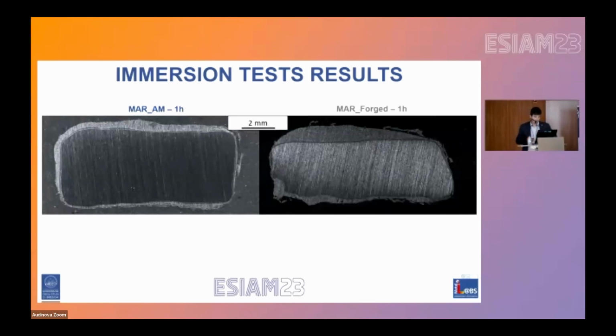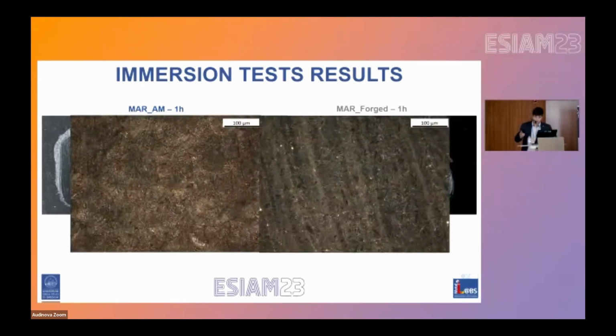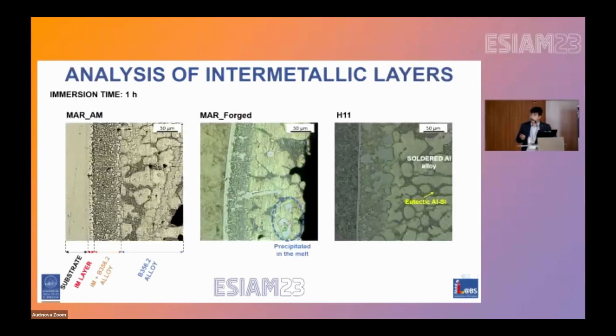This behavior could be correlated with the different speed of the reaction between the steel and the aluminum, or could also be related to some effect related to the more uniform microstructure of the AM sample compared to the forged one, which presents the typical segregation bands of forged products. However, further analysis is needed to better understand this behavior.